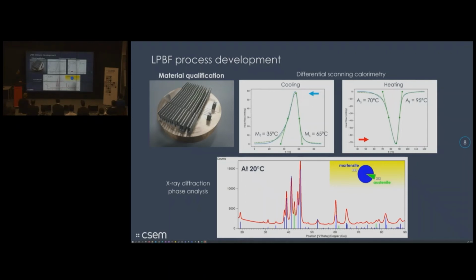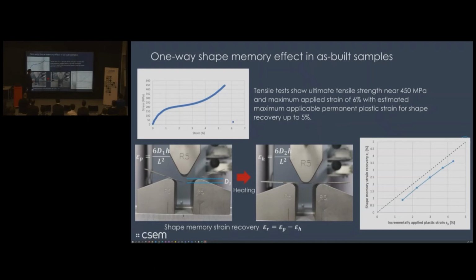So then we did the verification and validation of one-way shape memory effect and characterization. So here is one stress-strain curve. This shows the ultimate tensile strength near 450 megapascal and maximum applied strain at the moment of failure near 6%, with estimated maximum applicable permanent plastic strain for shape memory recovery up to 5%. This has been measured using three-point bending tests, where we observed up to almost 4% of one-way shape memory effect for strain recovery.